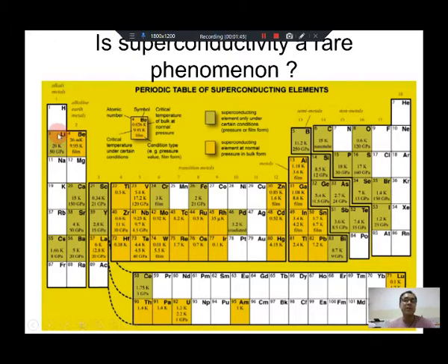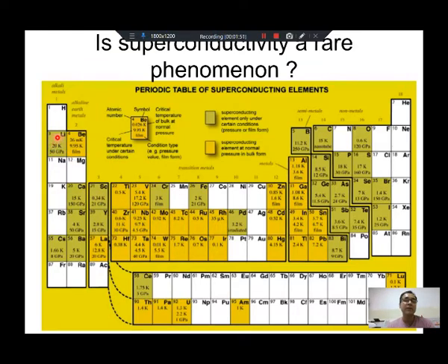For example, here you can see that lithium becomes superconducting with a critical temperature of 20 Kelvin at 50 gigapascals of pressure. Whereas beryllium, Be, for example, has a Tc of around 26 millikelvin, and 9.95 Kelvin actually in film form. So the lower Tc is for bulk, and if it is in the form of a film, then under certain conditions it can have a Tc which is relatively high.